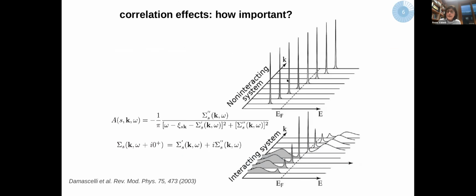Let me start with correlation effects, and how important they are in these materials. We start with a description of a non-interacting electronic system. We can describe the system in a k representation, so in the reciprocal space representation, as basically having quasi-particles that have an infinite lifetime. And now when we start to switch on correlations, a strong interaction among these quasi-particles, what we observe is a transfer of spectral weight into what we call the lower and the upper Hubbard band.